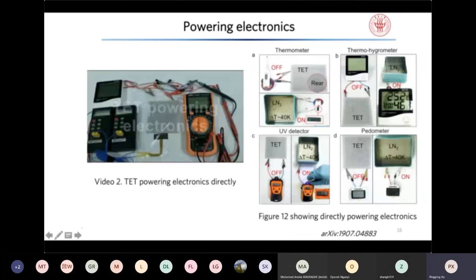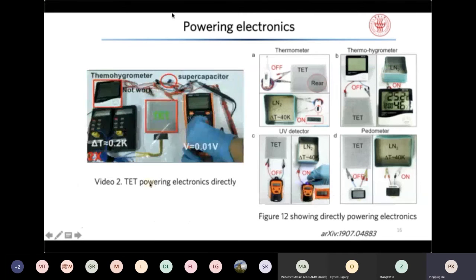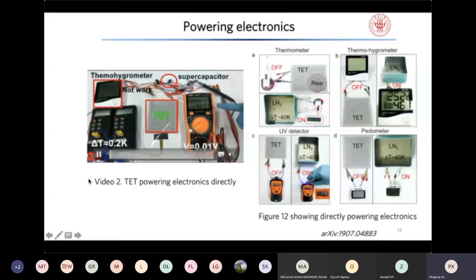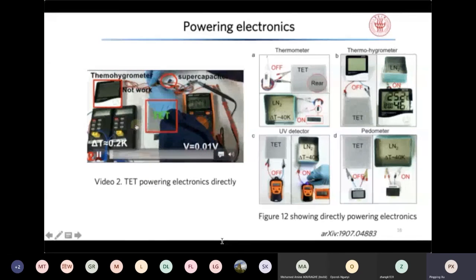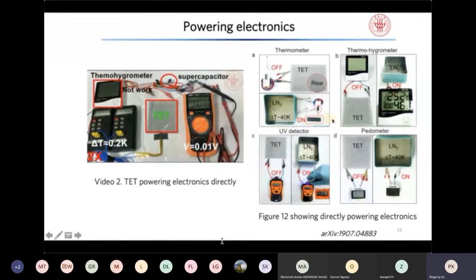All right. So this summarizes the power requirement for different electronics, and we can see that this is much lower than the power generated from the thermoelectric textile. And this video shows how we apply a temperature difference by liquid nitrogen, and then how we generate the power to power something. And also we can use the thermoelectric textile to directly power electronics like the thermometer, hygrometer, UV detector, and pedometer.